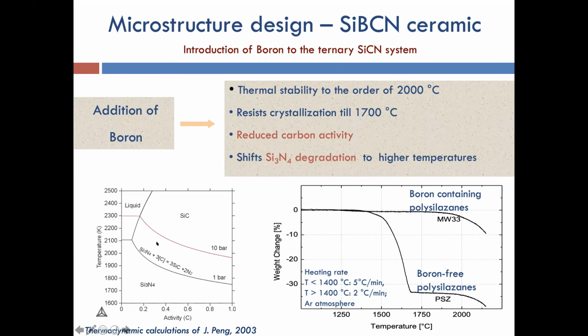On the left-hand side, I show you the thermodynamic calculations of the stability of silicon nitride as a function of carbon content. And you will see that, of course, depending on the nitrogen partial pressure, the silicon nitride stability would increase to much higher temperatures if you have a high partial pressure of nitrogen. But the point here is that if the carbon activity is reduced to a large extent, then the dissociation temperature, or the silicon nitride stability, would increase. So that's what we would expect, and that's what we wanted.